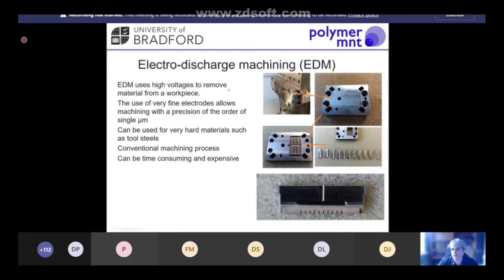So this is actually one of our microneedle molds at Bradford, and this consists of a kind of three-sided pyramid type shape microneedle. And this is created by 11 laminates, so 11 strips of metal that have the microneedle form etched into them using an electro-discharge machining technique. So you can see in the picture on the bottom, we can see our needle forms at the bottom of that laminate there. We assemble this with its partner laminate, and then we assemble all 11 laminate parts together into our mold tool, and that creates our microneedle array.